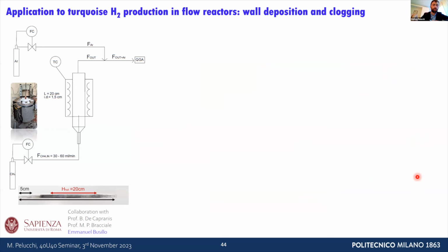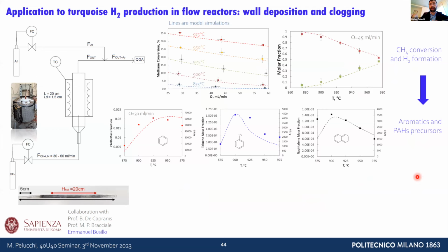We're also working with the University of Rome La Sapienza on the production of turquoise hydrogen and carbon material. This is a comparison between our model and some methane conversion as a function of different residence times or flows into this quartz reactor, and the mole fraction of hydrogen formation as a function of temperature. We were also able to identify and quantify some aromatics, again a comparison between model and experiments.